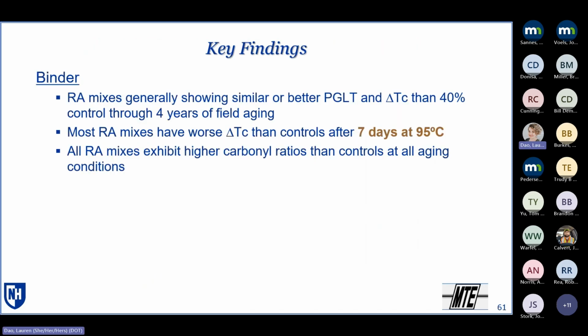So just summarizing what we found so far from this phase of the testing results. From the binder testing, our RA mixes generally show similar or better PG low temperature and delta TC than our 40% controls through the 4 years of aging. When you look at the delta TC, they're a little bit worse, especially at the longer term aging. And as I mentioned, they've got the higher carbonyl ratios for all the aging conditions.